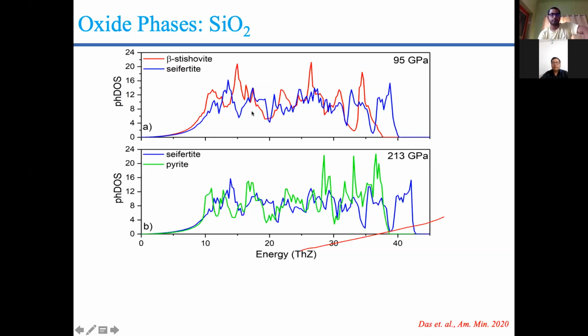If we just concentrate on the lower frequency region, you can see that beta stishovite has higher population than seifertite. As seifertite is the high pressure phase, if we subtract the entropy of seifertite from beta stishovite, we will find a negative change of entropy, which supports our result. Secondly, if we go for the seifertite to pyrite transition, the pyrite has the higher one. That means this transition is supported.